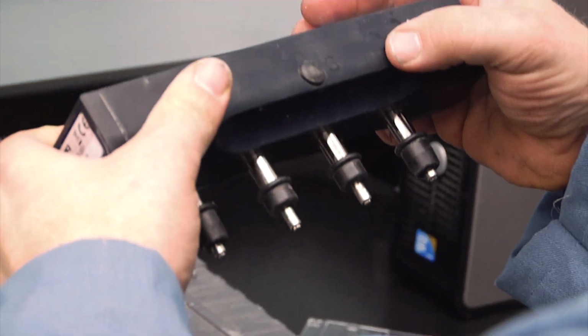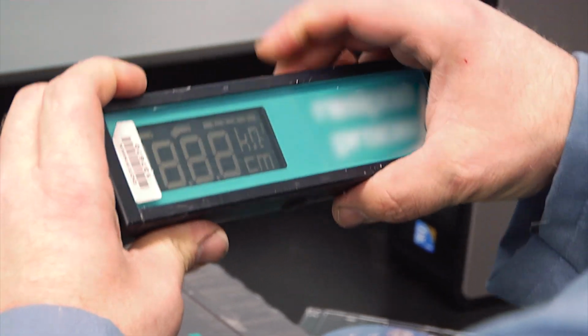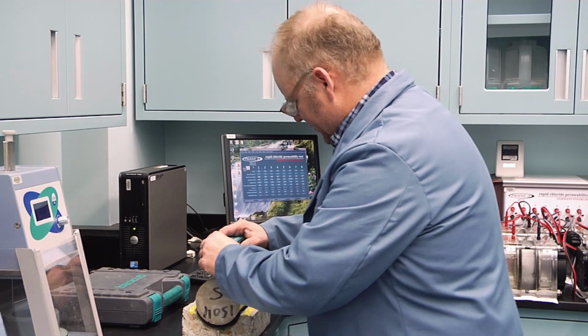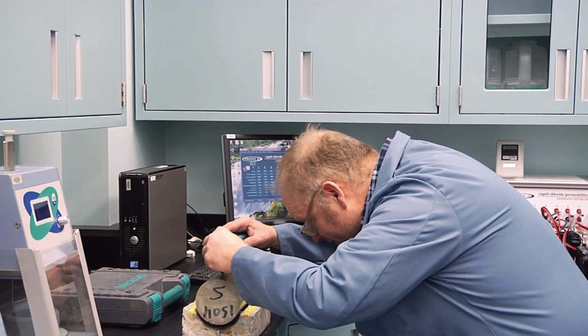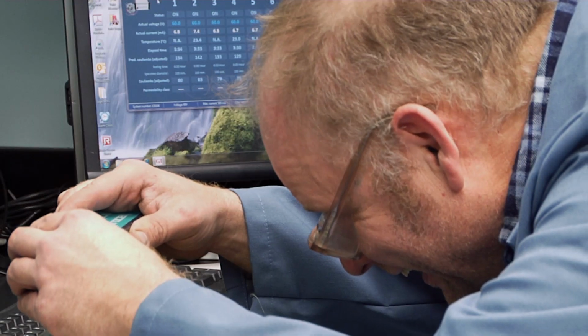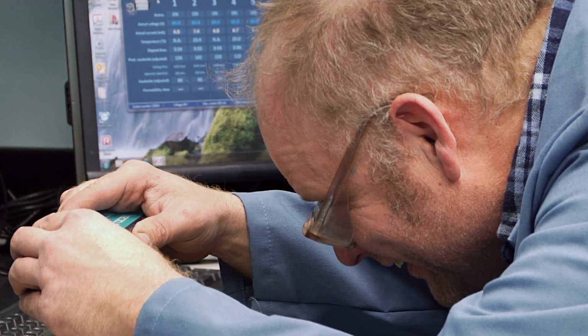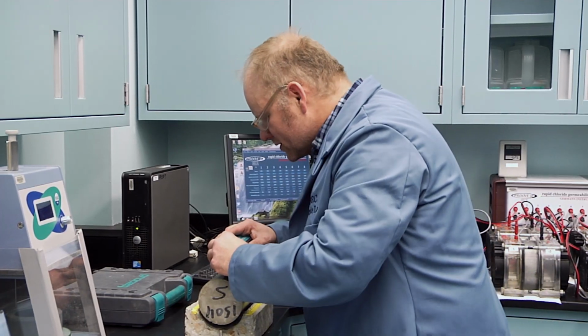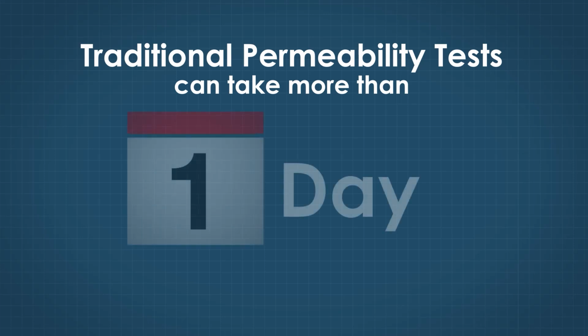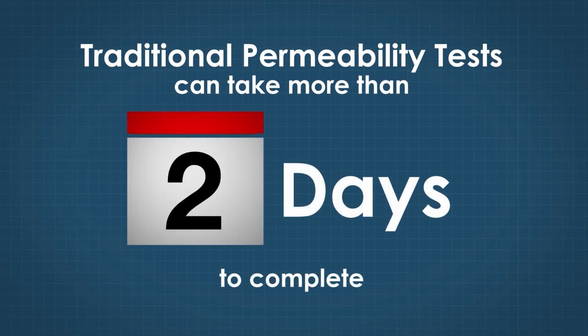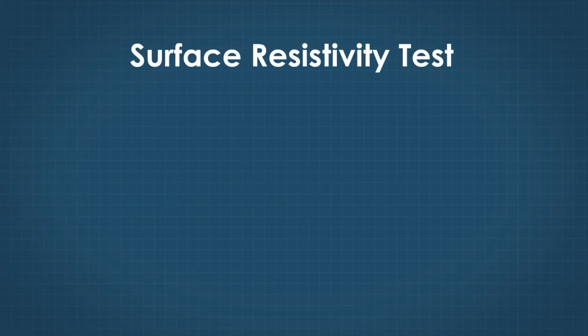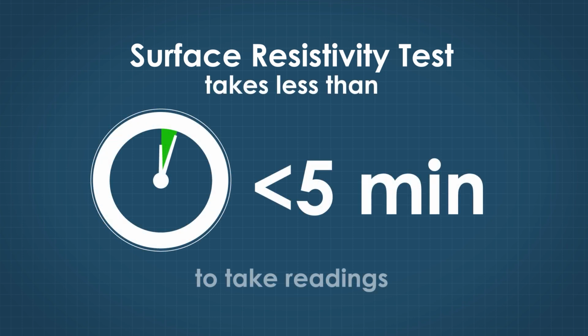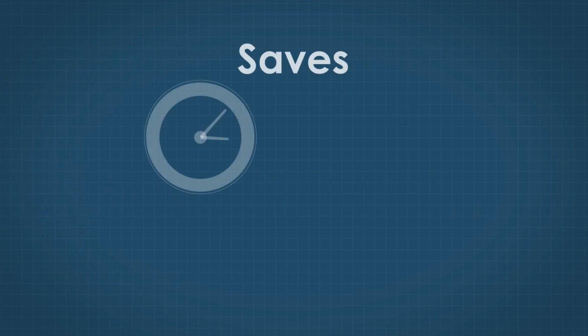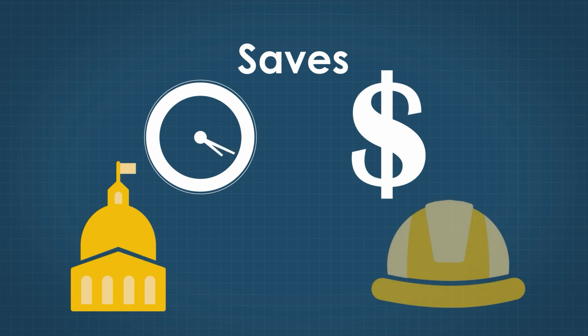The surface resistivity meter basically has 4 probes on it. The outer probes apply voltage and the inner probes measure current. And using Ohm's law, we can measure resistance. And from resistance, we can calculate resistivity. Checking the concrete's permeability is very important during mixture design and during construction of highways and bridges. Traditional tests can take more than 1 day to complete, but the surface resistivity test takes less than 5 minutes to take readings, which saves time and money for agencies and contractors.